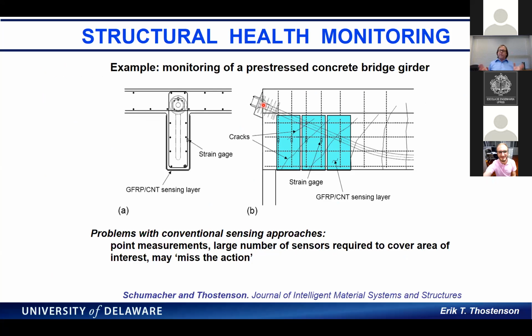So we thought at the very beginning, well, can we utilize this and create a distributed patch in order to detect cracks in whatever it might be. In this case, this is a pre-stressed concrete bridge girder. And what happens is over time you get these shear cracks, and can we use these U-wraps to detect the damage? One of the things that's often done is if you put a strain gauge on the specimen, and you don't have a strain gauge sitting right on or very near the crack, you don't really pick up the action. In this case, we could have a truly distributed sensor that would be able to detect those cracks.